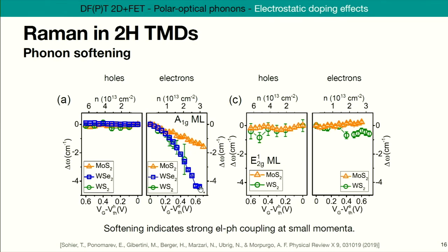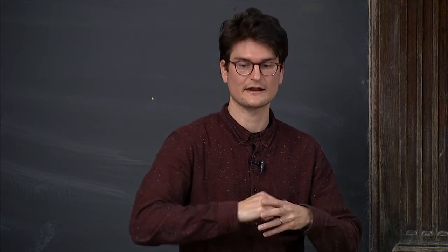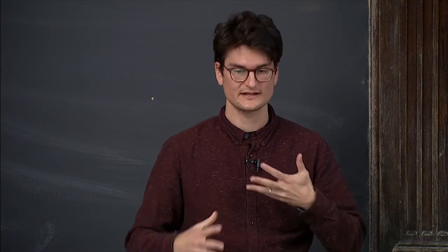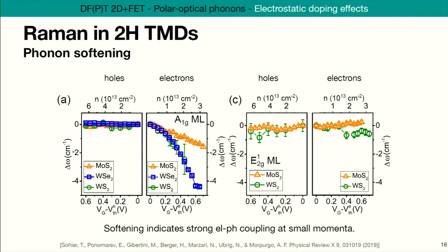For which the frequency goes down. So we call this softening, because essentially the frequency going down means the phonon is less energetic, so it's kind of softer. And usually this kind of softening indicates a strong electron-phonon coupling at small momenta. So you can see it as electrons and phonons conspiring to get the energy of the phonon a little less costly, to make it a bit easier for the phonon. The electrons are kind of helping out here. But this works only if there's a strong coupling between the two. Otherwise, there's nothing happening.